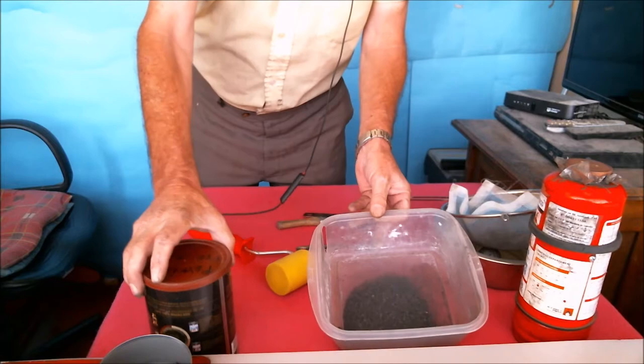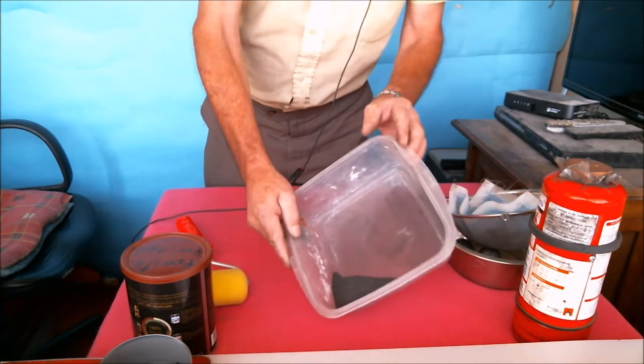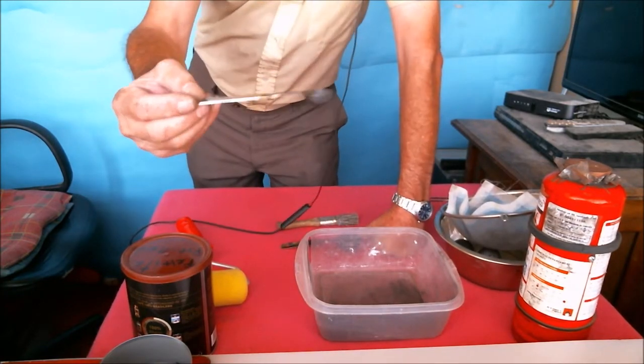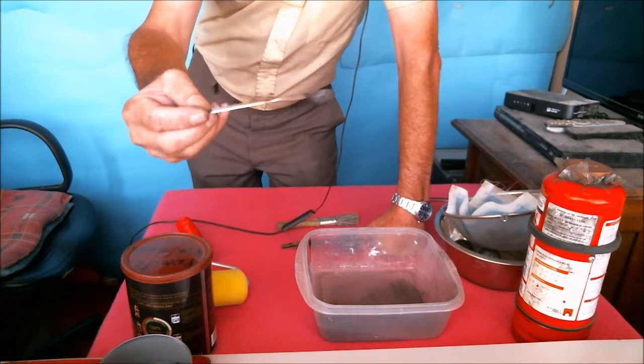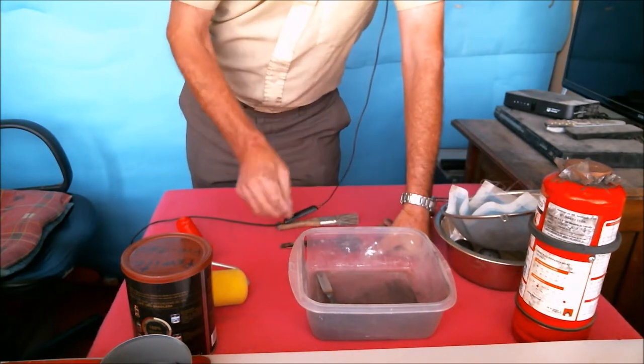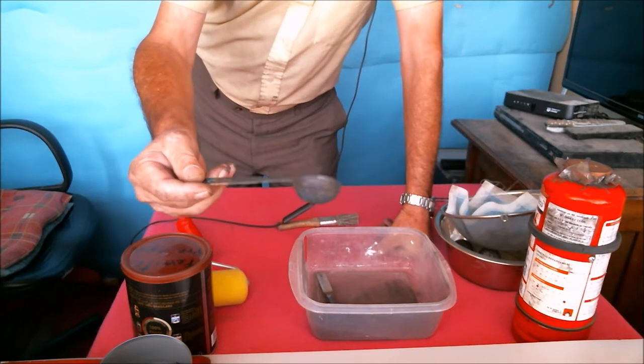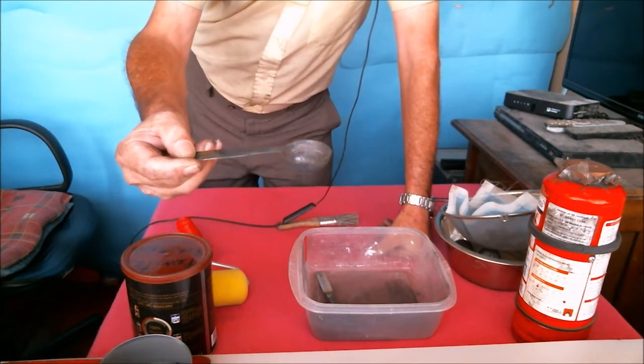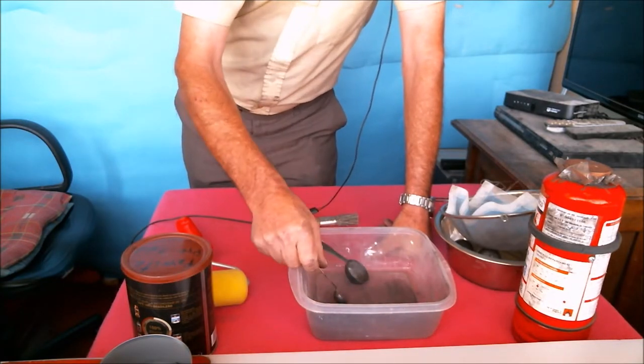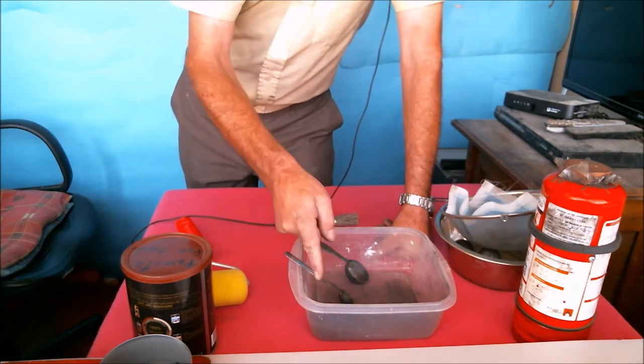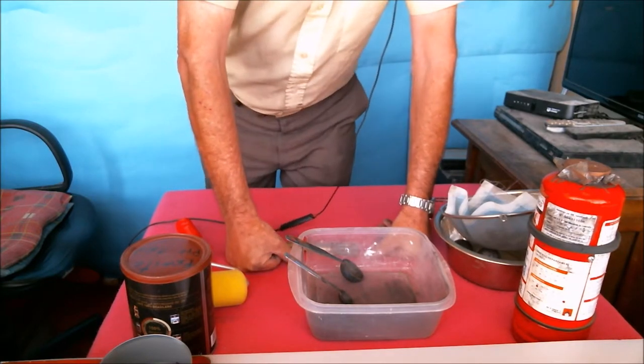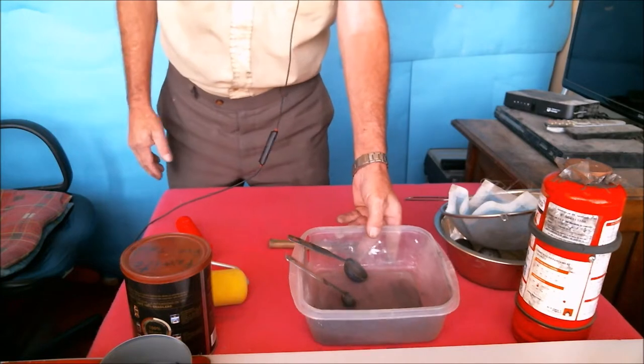Then once I have the ingredients, a good amount of ingredient, I have used this measure that is half a teaspoon. I use two of these, that is one teaspoon of ferrite mixed with this measure that is one tablespoon of paint, water-based enamel. Okay then this in total would be one teaspoon of ferrite and one tablespoon of paint. That's the formula I have used till now for my best paint.